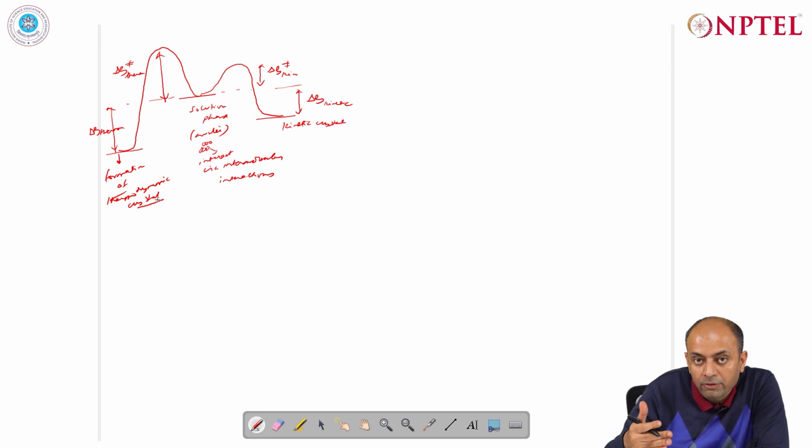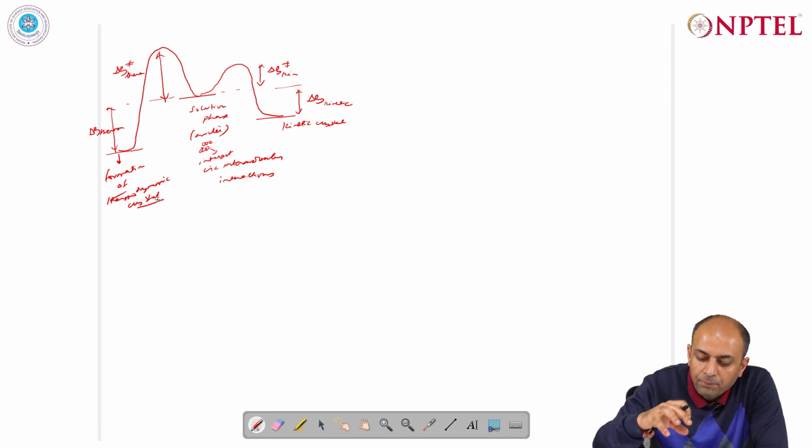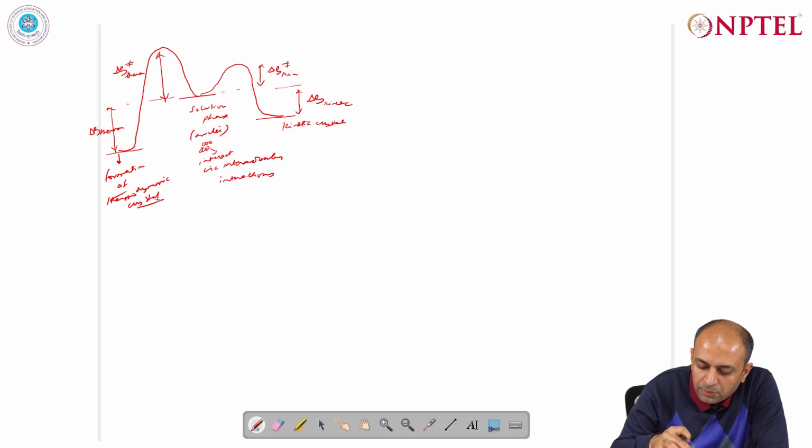If you give very fast evaporation rates and high temperatures, then the tendency to get a kinetic crystal is high. But if you allow the system to equilibrate with the surroundings and you gradually lower the temperature of the system very slowly, you really reduce the rates of evaporation significantly, then statistically you are promoting thermodynamic conditions of crystallization. So the barrier can be higher, but it will give you the thermodynamic crystal, and once the thermodynamic polymorph is formed, it will not convert into the kinetic polymorph.